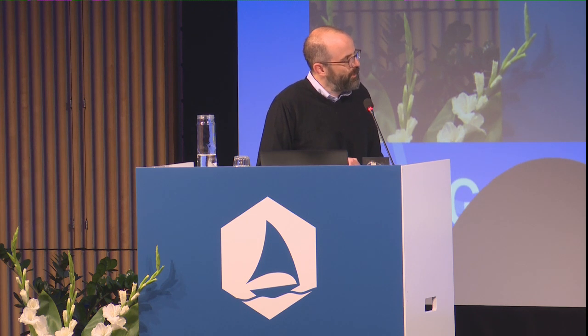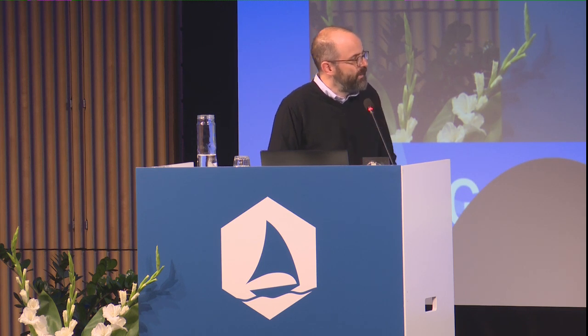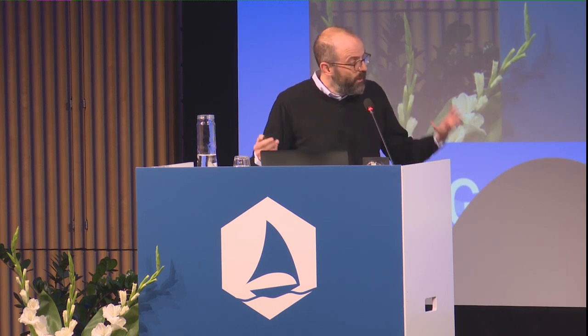So now what was realized was that the minimum bandwidth is achievable basically when this energy scale matches this energy scale. And you can get to that point by twisting in a finely precise way to exactly the magic angle. So I rotate these cones in such a way that this energy scale now matches this energy scale, and in that condition I get the minimum bandwidth. That's called the magic angle when that happens. So that magic angle is 1.1 degrees.